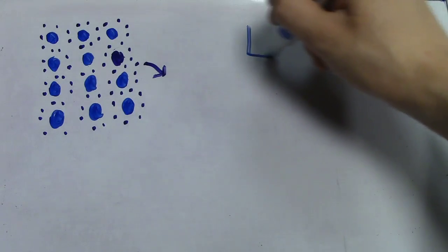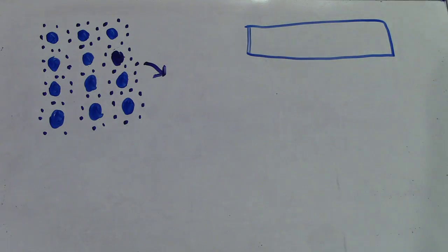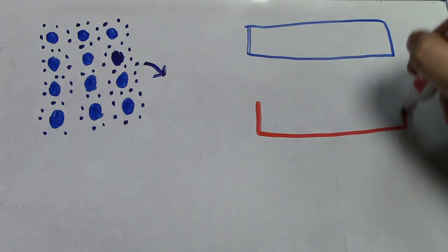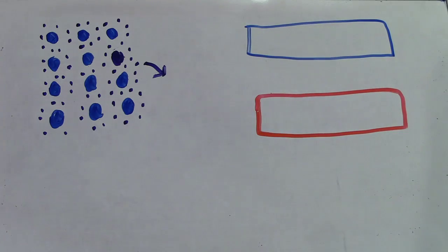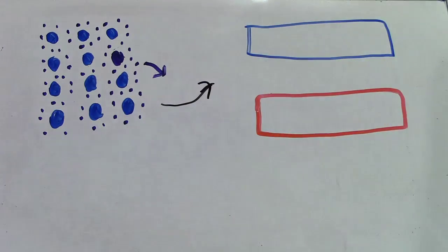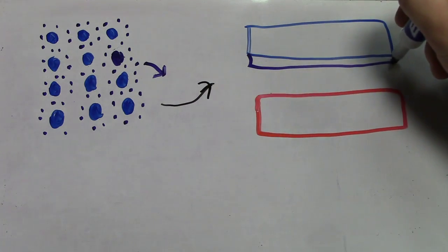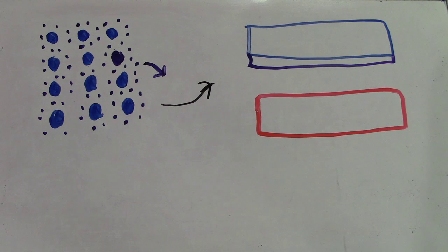In this situation, the phosphorus atom only really wants 4 of its electrons, so the 5th can be dislodged with only a small amount of energy. This can be interpreted as decreasing the energy band gap by adding an energy level right below the conduction band. Doping a semiconductor in this way, that adds an electron, creates an N-type semiconductor.